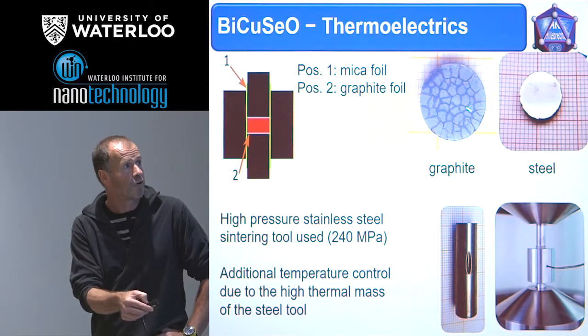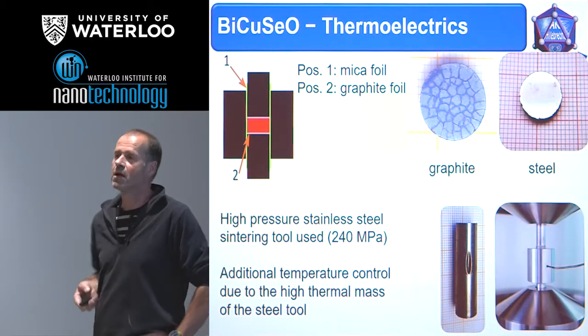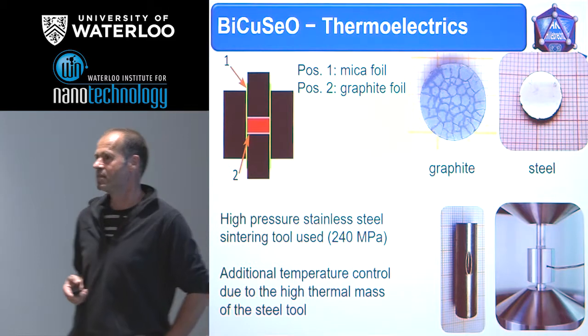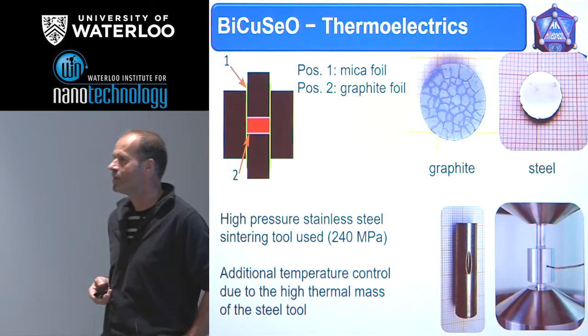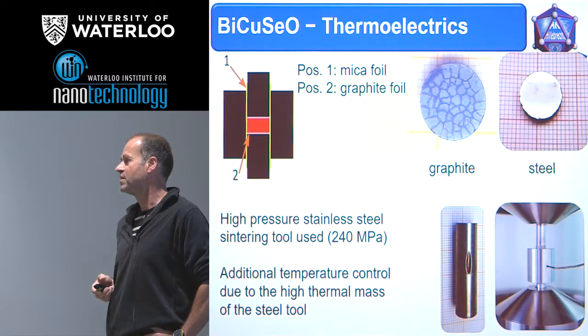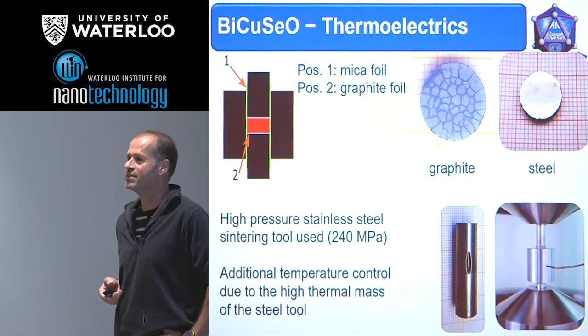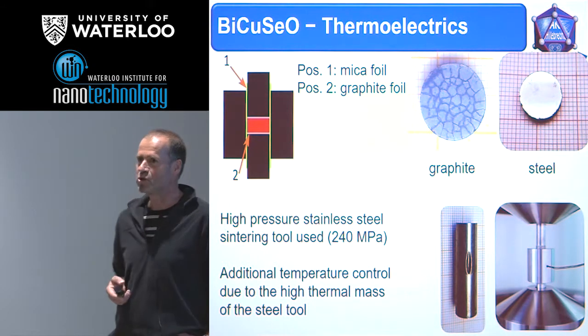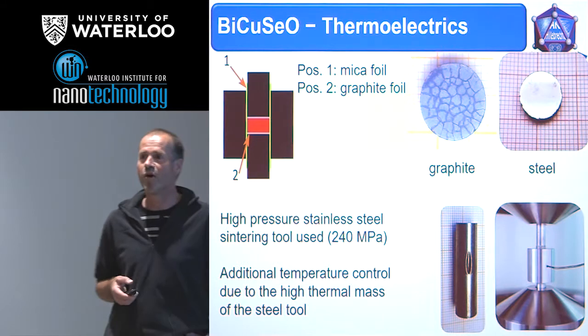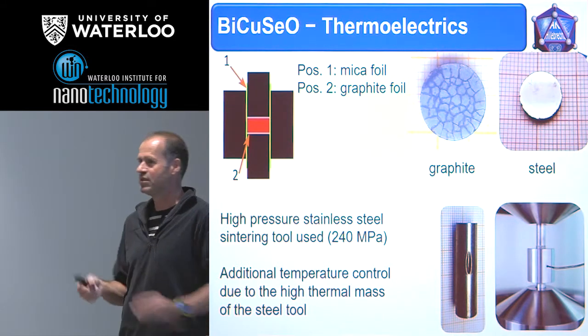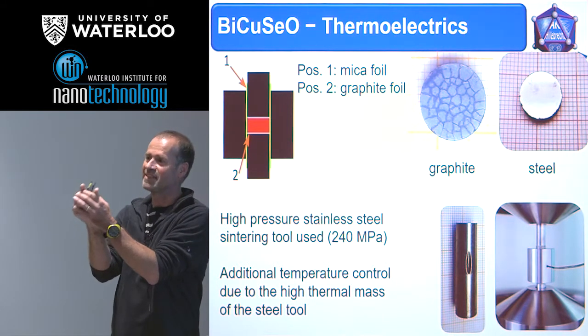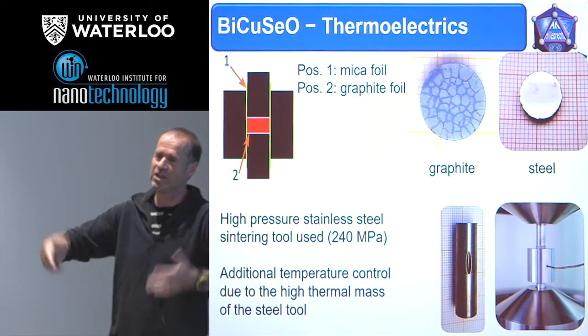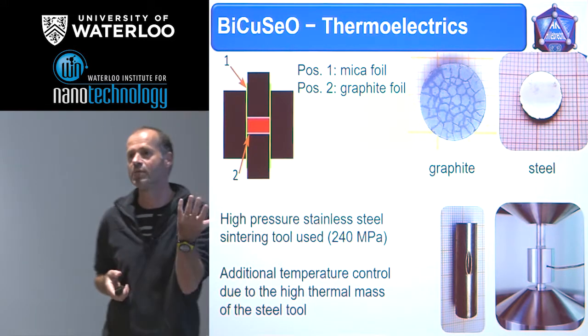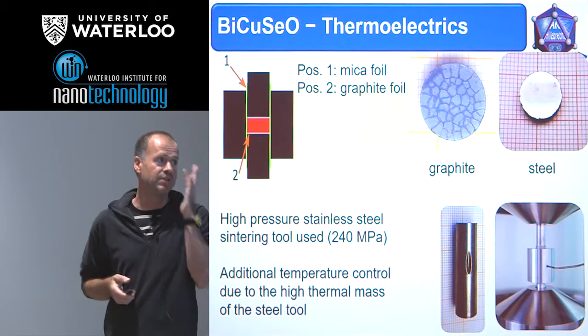If we look at the usual pellets, we see that there are lots of cracks, and it is not possible to get reliable data for the thermoelectric properties if you have cracks in your sample. So some of the data which were published, we don't know how they were produced, because you need a well-developed sample without inclusions and cracks and so on to get reliable values for the thermal conductivity.